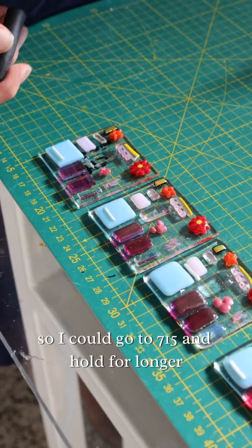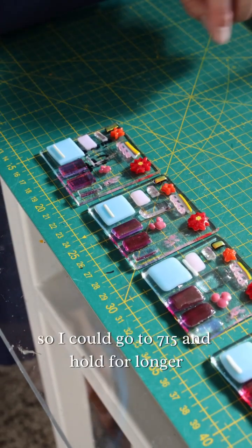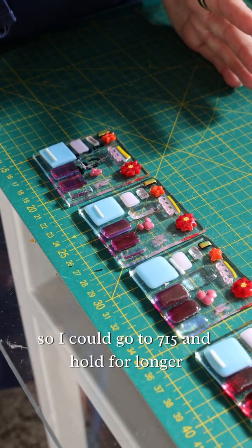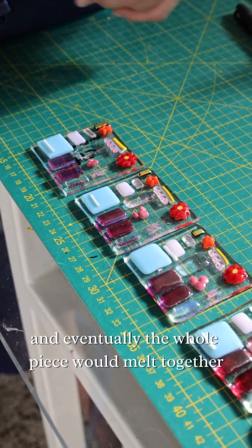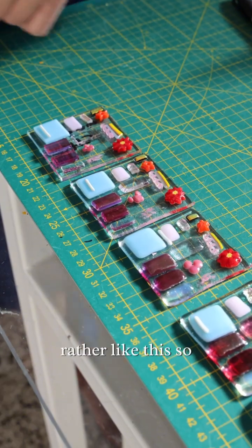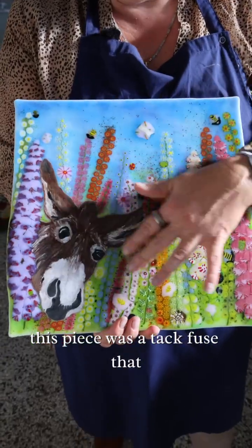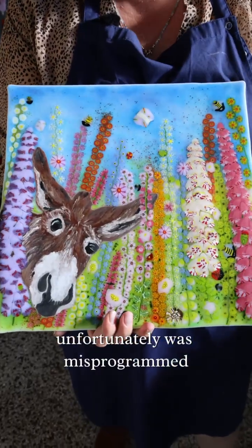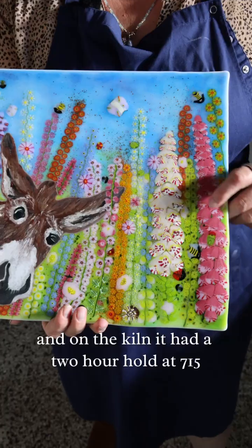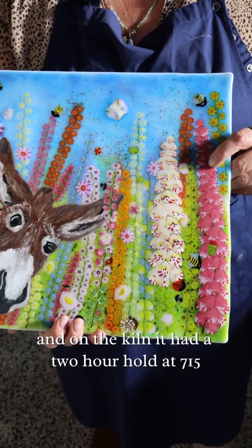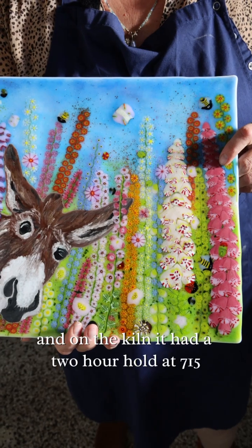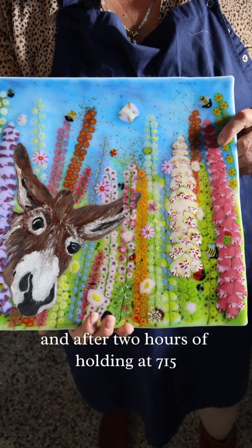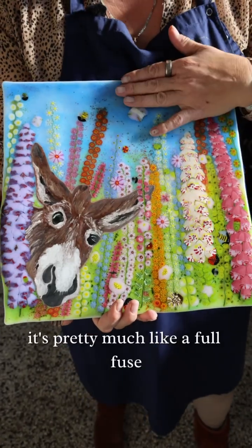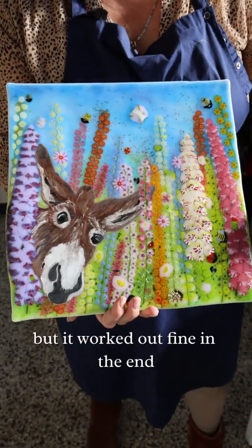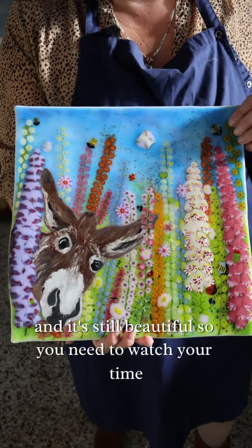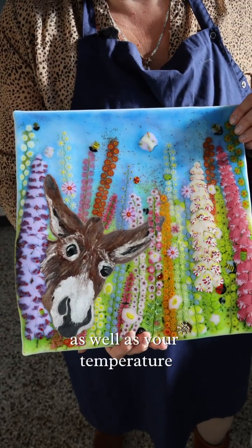So I could go to 715 and hold for longer, and eventually the whole piece would melt together, rather like this. So this piece was a tack fuse that unfortunately was misprogrammed, and on the kiln it had a 2 hour hold at 715. And after 2 hours of holding at 715, it's pretty much like a full fuse. But it worked out fine in the end and it's still beautiful. So you need to watch your time as well as your temperature.